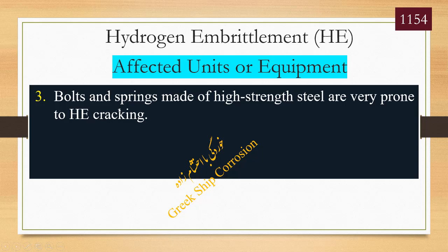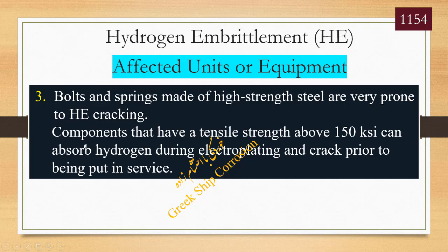3. Bolts and springs made of high-strength steel are very prone to hydrogen embrittlement cracking. Components that have a tensile strength above 150 KSI can absorb hydrogen during electroplating and crack prior to being put in service.